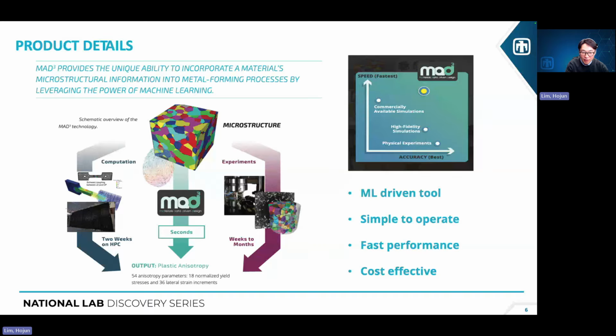it provides the directional strengths, or the anisotropy, or the thinning ratios, what we usually call R values, as well as material data or parameters for different yield models, which you can directly incorporate in any continuum scale simulation software. So again, the MAD³ has a big advantage in speed versus accuracy, if you see on that top right corner. And it uses a pre-trained machine learning tool, so that eliminates the need for expensive experiments or simulations. So it is easy to operate, it is fast and cost effective.